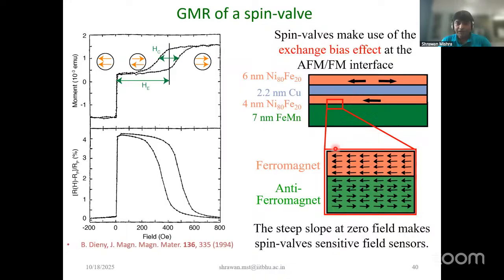So not only does the resistivity change, but the overall magnetization of these devices also changes. So now instead of one ferromagnet, here I have 7 nanometers, and on top there is 6 nanometers. Now the magnetization of this entire device is not going to behave like a pure ferromagnet, but this device's magnetization property will be coupled through this interface. So now two ferromagnets are coupled through the copper, and this will give this kind of magnetic hysteresis.